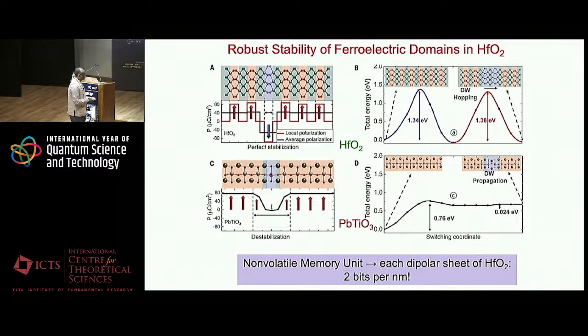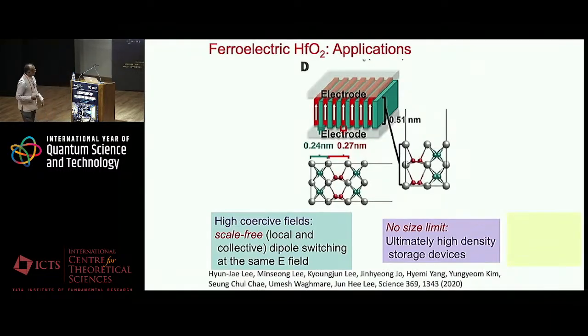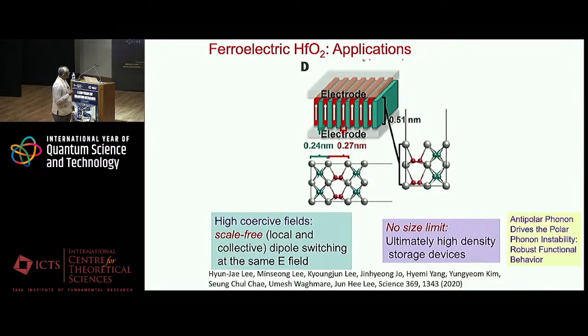So you have 2 bits per nanometer possible in terms of memory storage, and that's really remarkable. In fact, the limitation on the density of memory will be determined by how small electrodes you can deposit on it, and the material. Second advantage is it's a 3-dimensional crystal architecture. It doesn't require experimentalists to grow it in a nanoscale or fabricate in a nanoscale. You have a bulk film and you can make use of it just by patterning the electrodes on it. So ultimately high density storage devices are possible, and this was the work we published in 2020.